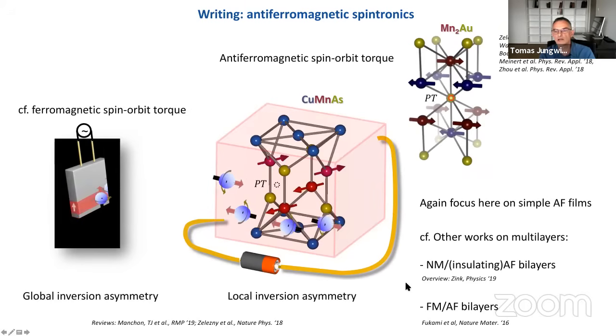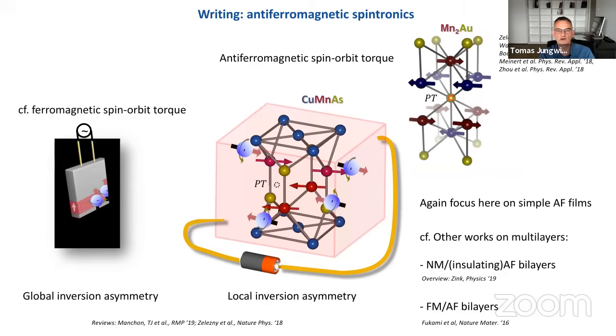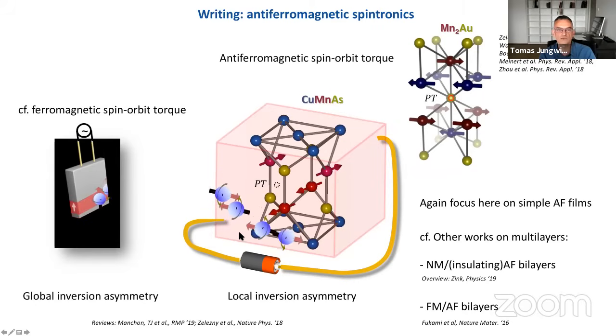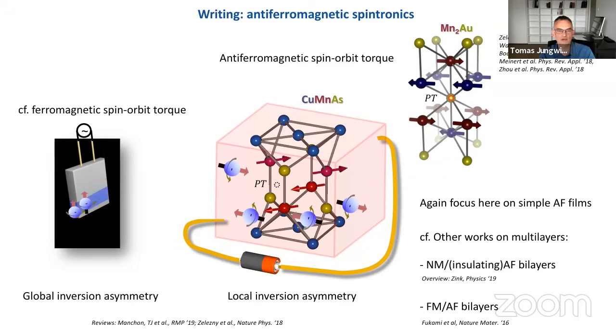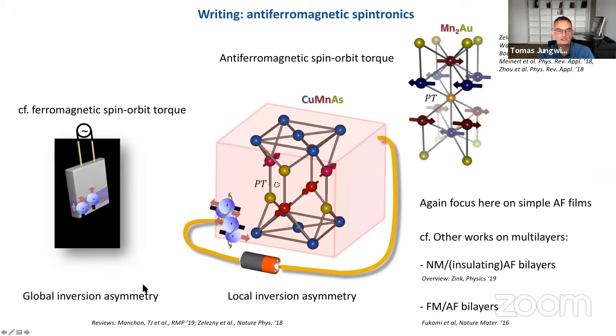Now, to adapt or modify this effect for antiferromagnets, the thing that we need to generate or control is the spin accumulation or non-equilibrium spin polarization, whose direction would flip when we go from one antiferromagnetic sublattice to the neighboring antiferromagnetic sublattice. And this can be achieved in systems where instead of having a global inversion asymmetry, we have a local inversion asymmetry at these magnetic atoms lattice sites.